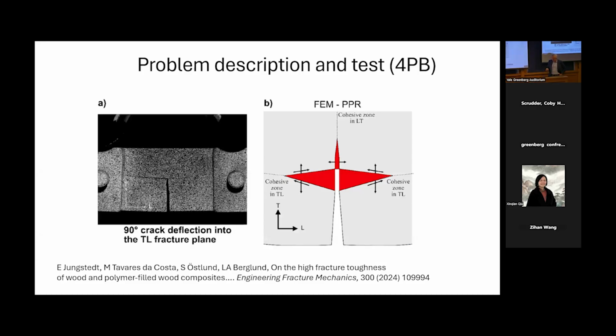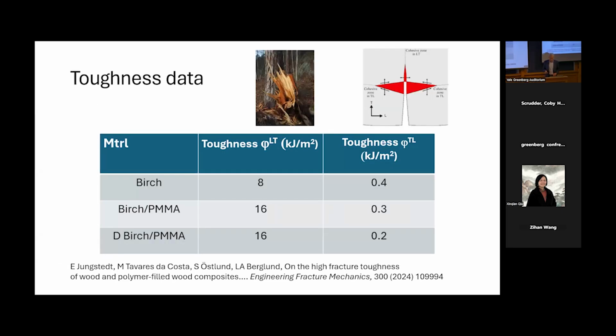So this is how we set up the problem. Essentially, we're driving a crack. We have one failing law for the transverse crack and one for the crack propagating. And if we look at the data, we can conclude that the toughness is about twice as high for the composites, and it doesn't matter, this nanoscale tailoring, for this particular property. Whereas in the other direction, when it grows like this, the material is really, really weak and brittle.